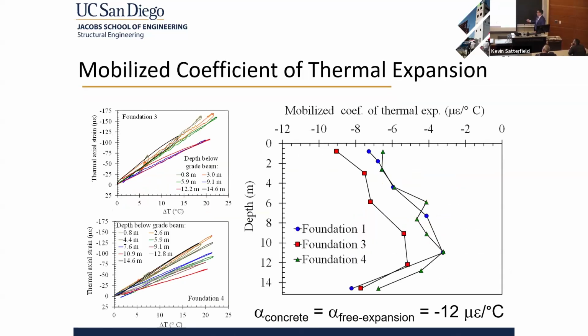The next thing we looked at are these mobilized coefficients of thermal expansion. Everything is linear, which is good. And if it was able to expand freely, it would have a coefficient of thermal expansion of about 12. So in the center of the pile was where the most restraint was located. We expected that the toe would have more restraint, but because of that loose material due to the construction technique that the contractor used, it was softer than we expected. We expected that this would go down.